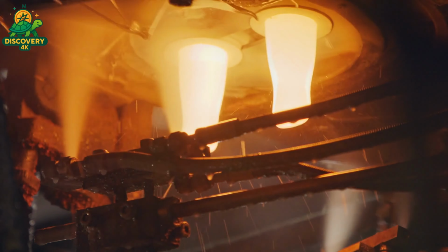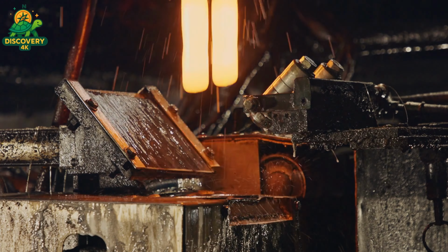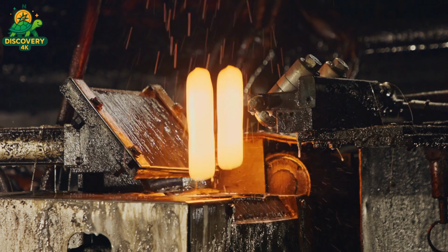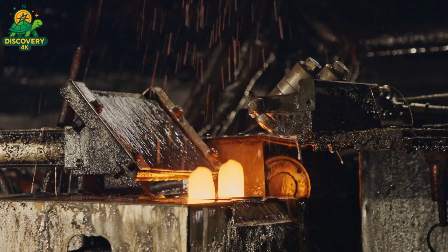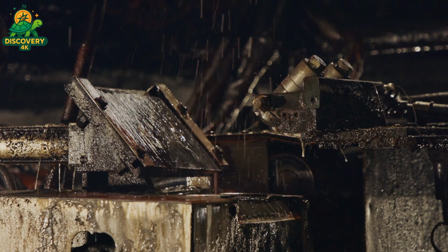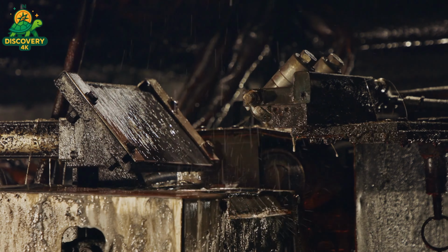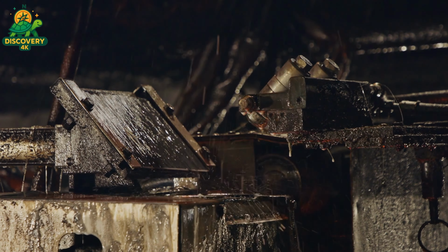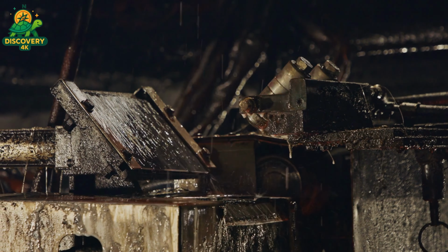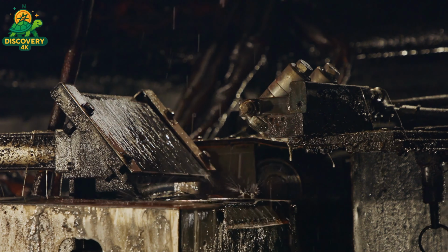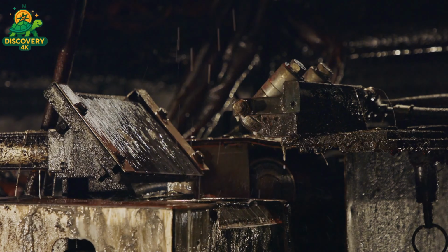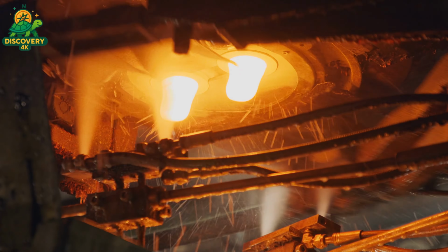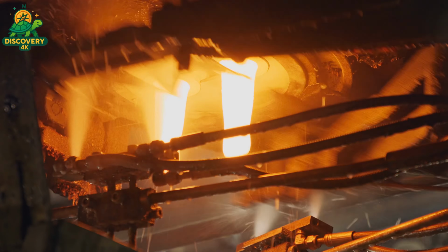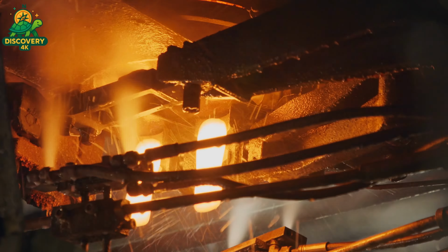Step 1. Gob delivery. Glowing orange gobs of molten glass, each weighing just the right amount for a bottle, are cut from the stream and dropped into blank molds. These molds are made from cast iron or nickel alloys, capable of withstanding extreme heat and repeated use. Step 2. Parison formation. The gob is pushed downward using compressed air or a plunger, creating a preliminary shape called a parison, a partially formed bottle with a hollow center. This step is critical. The parison determines the eventual wall thickness and bottle strength.